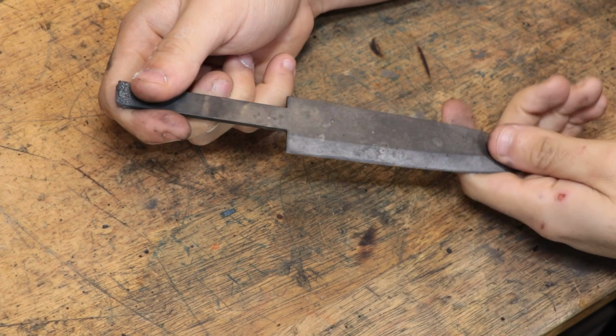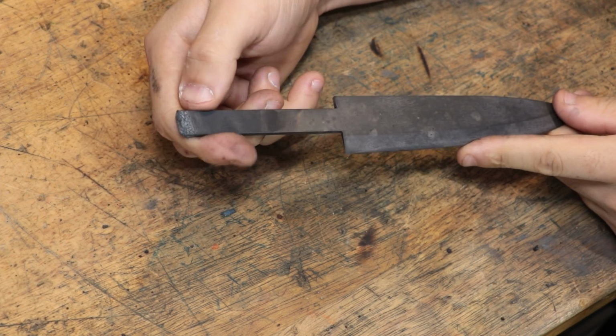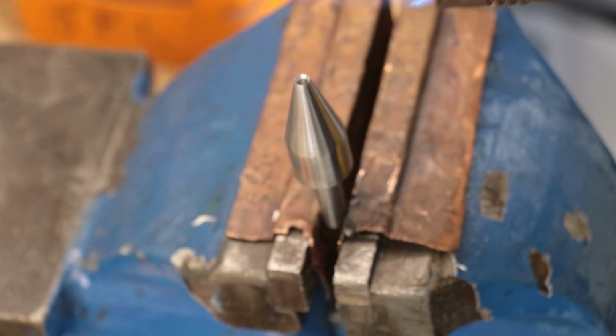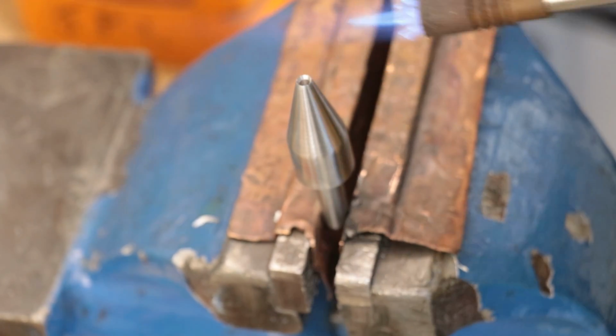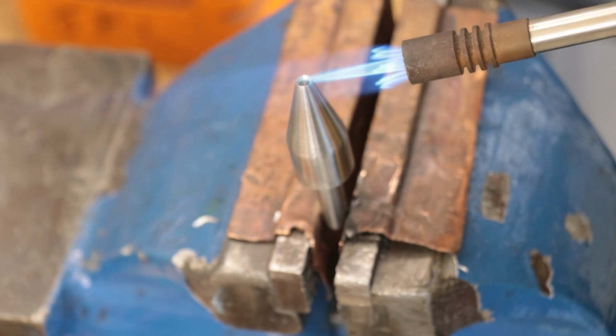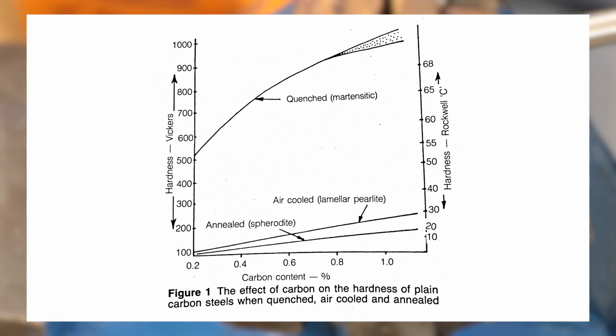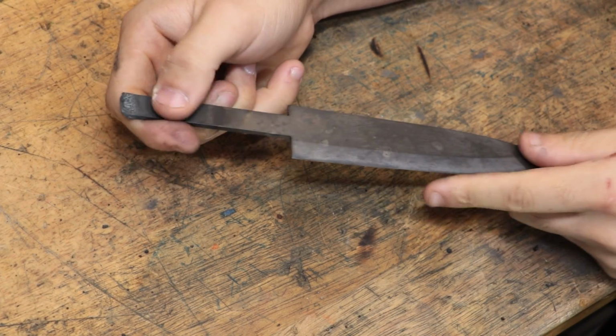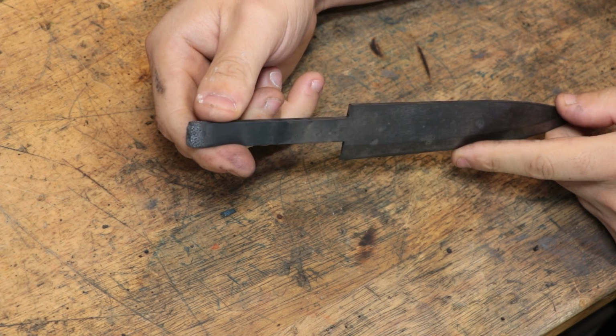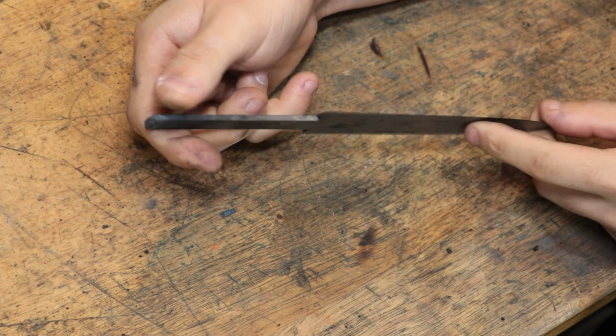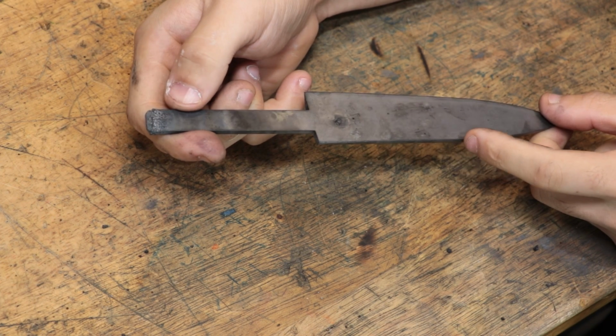Now it's worth pointing out that the overall carbon content is going to determine the maximum hardness that we can get, although it is not perfectly linear. 1045 won't get as hard as say 1095, however the difference is not that big. I've gotten close to 60 Rockwell C hardness with 1045, whereas 1095 only pushes about 68 Rockwell C hardness. With that said though, I generally don't ever know the final carbon content of the case harden, but I can very easily get 65 Rockwell C hardness.